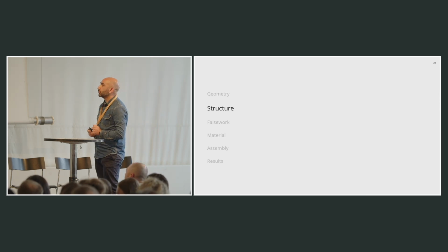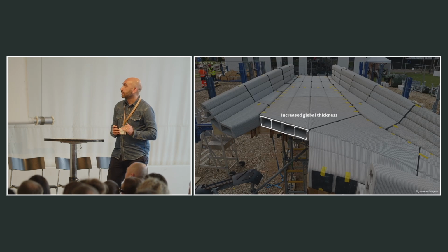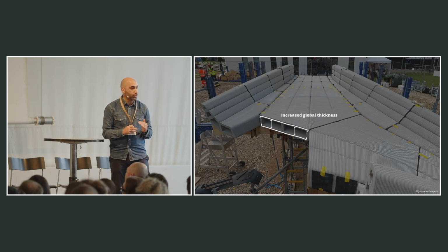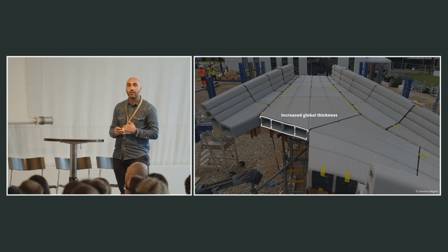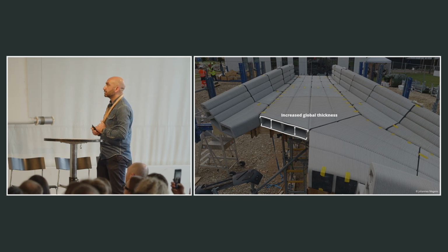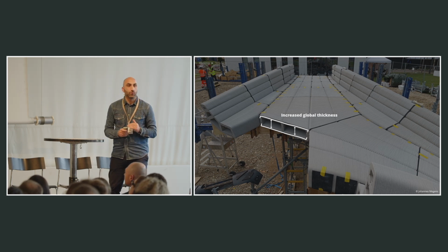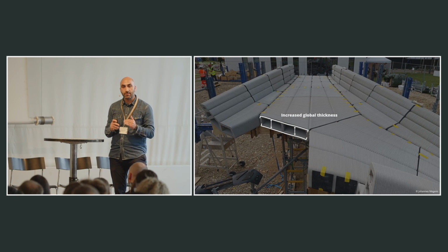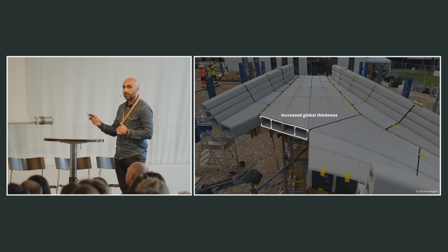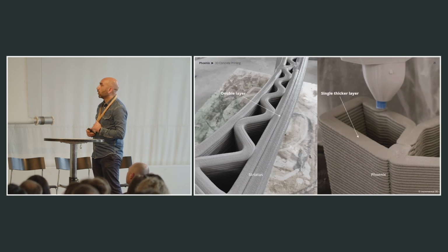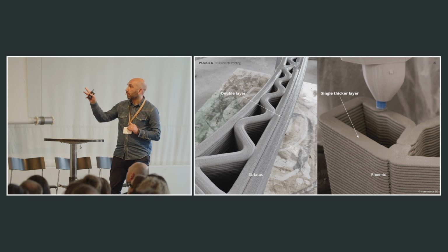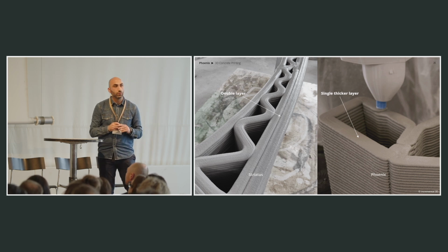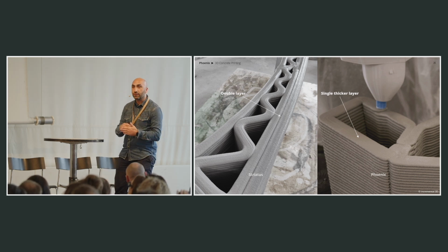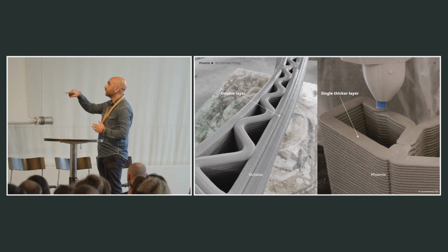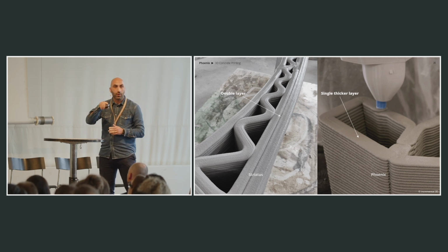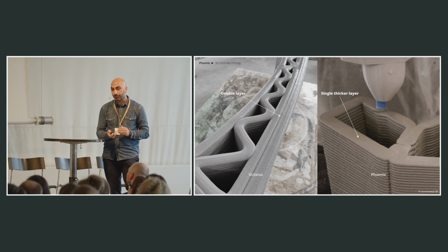From a structural point of view, we increased the global thickness of our geometry in order to increase the equilibrium solution space, especially for, for example, point loads or asymmetric loads, which are, let's say, the worst load cases for this type of structure. And locally, we also went from double layer printing, which could give rise to some cold joints between the layers, to a single thicker layer running around the 3D printed components.